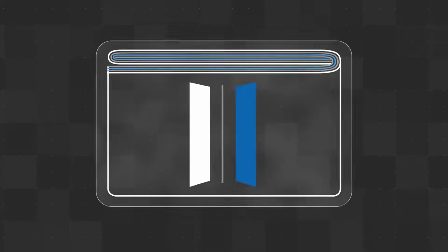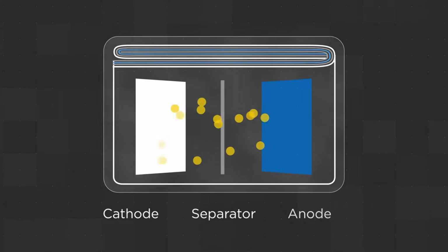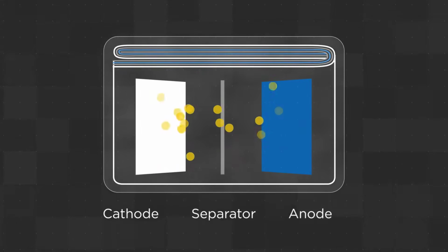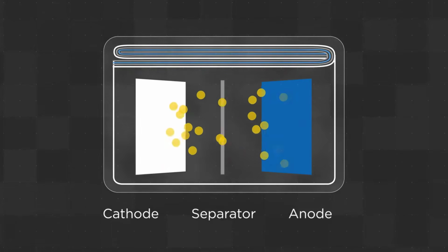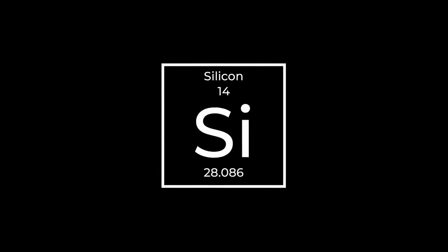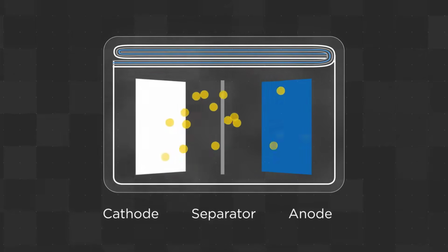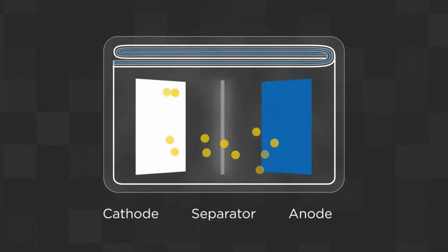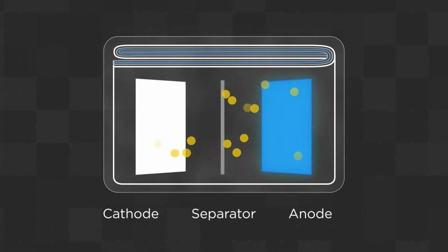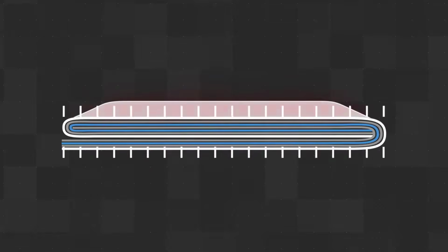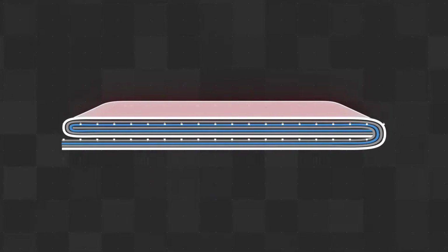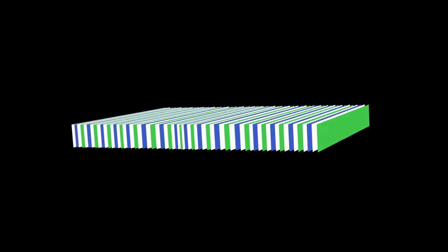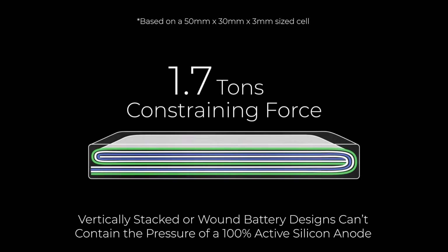To stand out from the big battery pile, innovation is concentrated on achieving a fundamentally new battery architecture that enables the use of a 100% active silicon anode, a long-standing goal in battery technology. Silicon can theoretically store more than twice as much lithium as graphite, but traditional jelly roll battery designs struggle with silicon's swelling and cracking. Enovix's stacked 3D architecture is engineered to accommodate this expansion by applying controlled stack pressure, improving